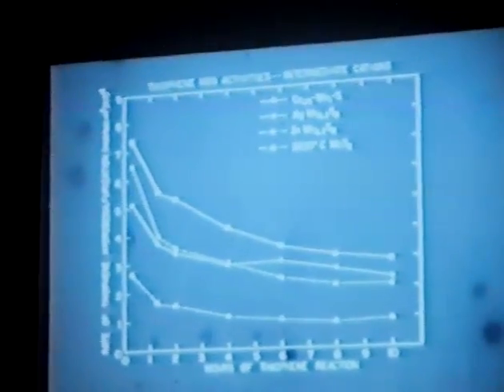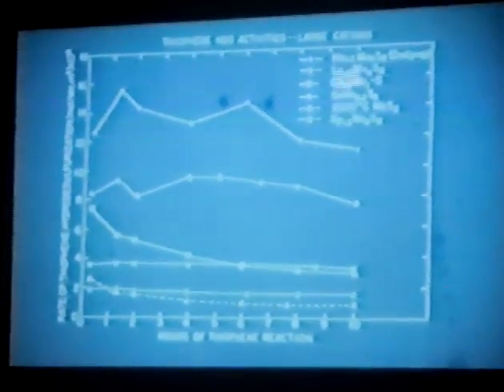When one goes up to the intermediate cation materials, we were really rather surprised, because when one starts to look at things like silver and indium, there's really not much basis here for thinking of these as being promoters. But again, if you think of the crucial idea here as being the oxidation state on molybdenum, which several of the people today have even talked about, what we're really doing here is just feeding electrons into the molybdenum. And what we're doing here is increasing the number of d electrons and looking at more reduced phases. So in essence here, maybe it isn't so surprising that some of these promoters are successful. One of our most successful Chevrel phases still remains this holmium phase, which has catalytic activity 2 or 3 or maybe even 4 times greater than the cobalt Topsoe type compound. Tin, lanthanum, a lot of the rare earths are very active Chevrel phase compounds.